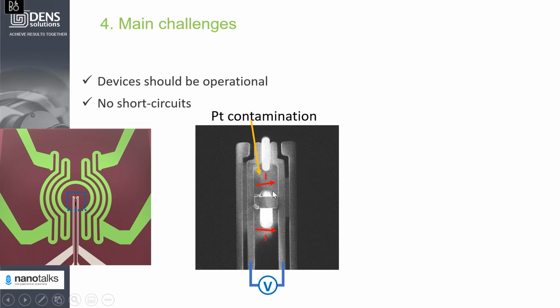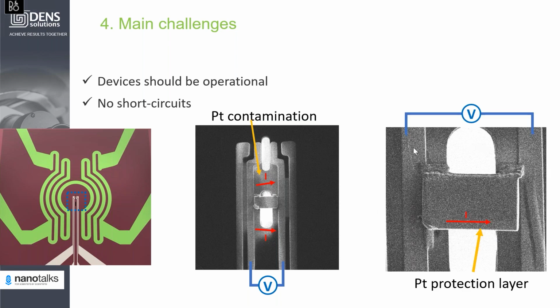If we apply a voltage bias to it, then basically the current, instead of going through your sample, will go via the least resistive path. So basically it will go via the platinum contamination. In this case, you will not be able to measure your sample. Another example is if you prepare a lamella, make 2 contacts with the biasing electrodes, and apply voltage bias again. But here we have a platinum protection layer, and if your sample is more resistive than the platinum protection layer, the current again will go via this layer, and you will not be able to measure your sample. You'll measure something else.